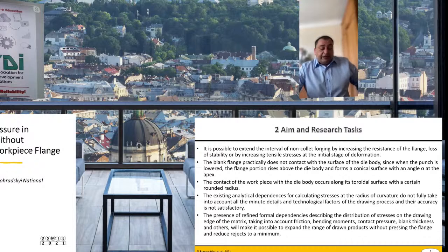The existing analytical dependencies for calculating stresses at the radius of the curvature do not fully take into account all the minute details and technological factors of the drawing process, and their accuracy is not satisfactory. The presence of refined formal dependencies describing the distribution of stresses on the drawing edge of the matrix, taking into account friction, bending moment, contact pressure, blank thickness, and others, will make it possible to expand the range of drawing products without pressing the flange and reduce rejects to a minimum.